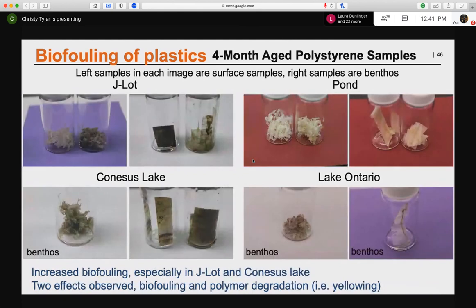As Christy was saying, we have recently done the 4-month sampling, and we have pictures of these as well. Here is the biofouling after 4 months in the environment. A couple of things to note. One, especially if we look at JLOT, look at that sample from the surface. The biofouling is to a very large extent now, and this has increased even from the first sample.